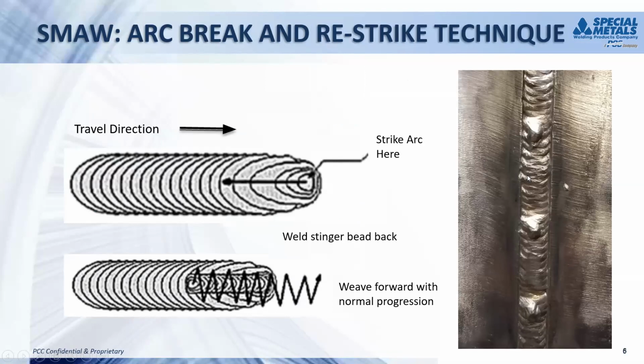As Sam mentioned, the start and arc break and restrike is very critical with stick electrodes, mainly because the nature of creating a concave crater is very susceptible to cracking. What we have is an illustration of a good proper arc break and restrike technique for a stick electrode. The picture on the right is a modified version of that, commonly used on test plates and weld labs, where you're going to be machining or grinding off those start stops.